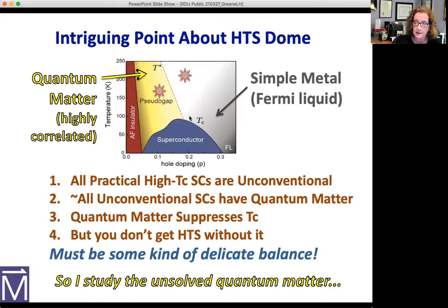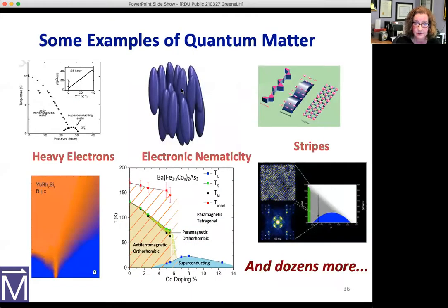So there's some kind of delicate balance between the strange kind of correlations that happen up here at high temperature and unconventional superconductivity. And that's why I spent the first few years studying this. Now I'm studying up here. So here's some examples. I told you this is heavy electrons. Above this dome here, the electrons get incredibly heavy. I mentioned the electron nematicity. These are my data. This is where it's superconducting down here. And this whole area here is where the electrons turn into these liquid crystal-like shapes. And here's something called stripes, where the electrons just line up across the sample.